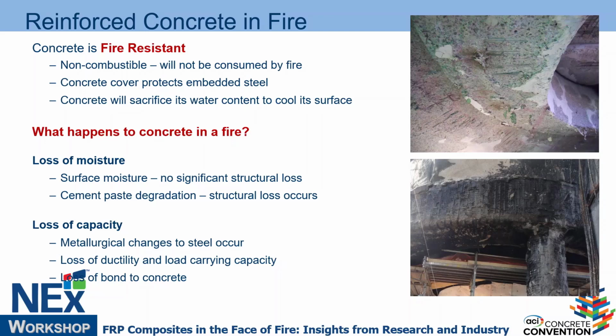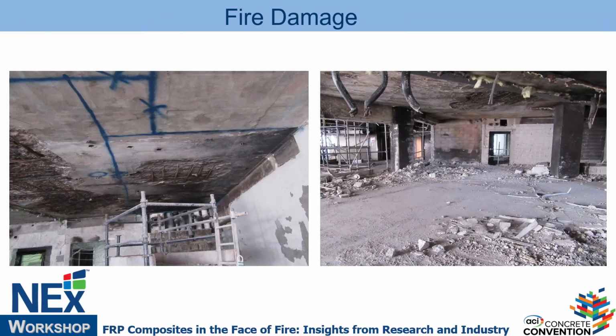The steel would go through metallurgical changes and then start losing ductility, stiffness, and also strength, right? And with that, as we go through fire, the strength starts dropping little by little, right? And it keeps dropping until at some point the strength will be so low that it can barely support its dead weight, right? And then we get collapse. We design, when we do a UL test, we do it for service. And I'll show you the fire load combination, ACI 440 for external strengthening and the ACI 562 code. It's really based on a ratio, trying to represent service with dead and live loads.